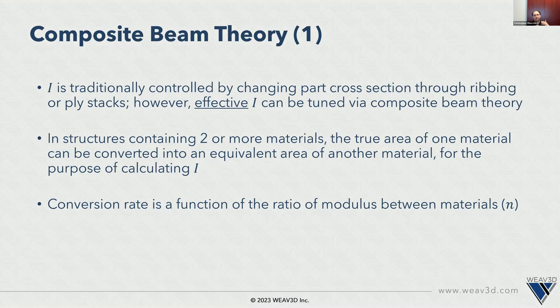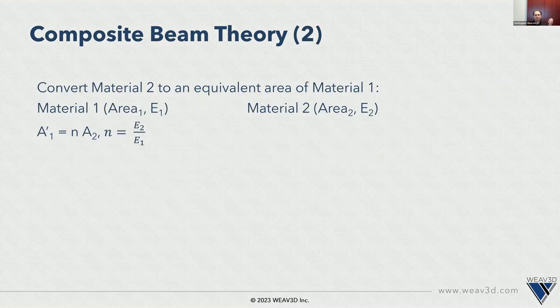So the way that this can be applied in this rebar for plastics concept is through something called composite beam theory. So we're basically saying you can use ribs or ply stacks of two different materials, and you can actually convert these two different materials into an effective I of one material based on the ratio of the two materials' modulus. So what that looks like practically speaking is, let's say you have a material 2 and a material 1. You want to convert them from one to the other.